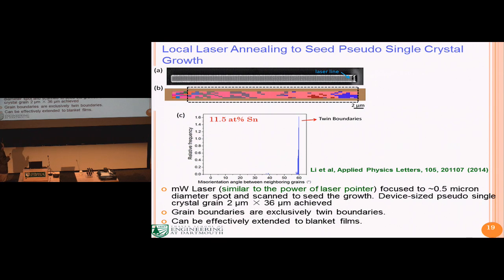Another way was accidentally discovered by Haofeng. He was doing the micro-Raman analysis. He found that if you use the maximum power and focus the light really well, the laser itself can actually crystallize the material. This is not a big laser you see cutting steel. Basically, this is a laser with a power similar to a laser pointer. But you focus the light so well to about half a micron diameter, you just quickly write through this. You can do the nucleation with the laser, and then you take the whole piece into a furnace. Basically, the crystal will grow from the seed.